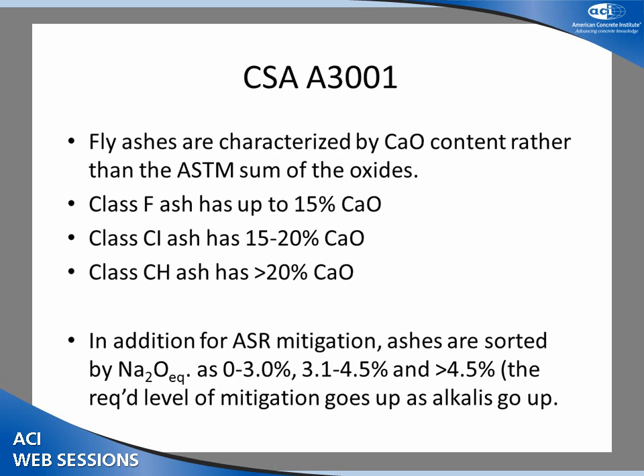The Class F ashes, instead of being 70% or more sum of the oxides, it's up to 15% calcium oxide. So it basically accommodates the Class F ashes that you would see here as well. And then we have two types of C ashes, 15 to 20% calcium and above 20%. The really high calcium ashes are ones that have some severe challenges in terms of durability concerns, like sulfate attack or alkali silica reaction mitigation. And the ones in between, the CI ashes, can often perform very well. Not always, so we require testing of the CI ashes. Well, we require testing of all ashes, but the CIs can be either really good or sometimes they behave more like a CH. But once they get above 20% calcium, then we have concerns about the durability issues.